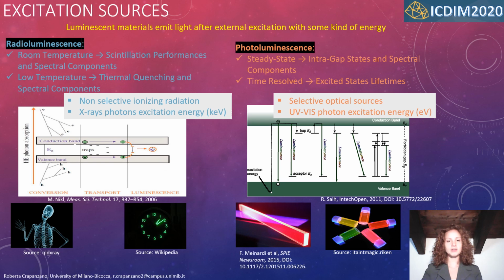The used spectroscopical techniques, radioluminescence and photoluminescence, exploit 2 different excitation sources, ionizing radiation and light respectively. In radioluminescence, the excitation is not selective and involves core states. In fact, when an X-ray photon is absorbed, its high energy is converted into a cascade of electron-hole pairs, which finally thermalize in the conduction and valence band respectively. Then the free carriers can migrate in the material, and several different relaxation pathways can occur. For example, they can be trapped by trap levels, or they can recombine on a luminescent center.